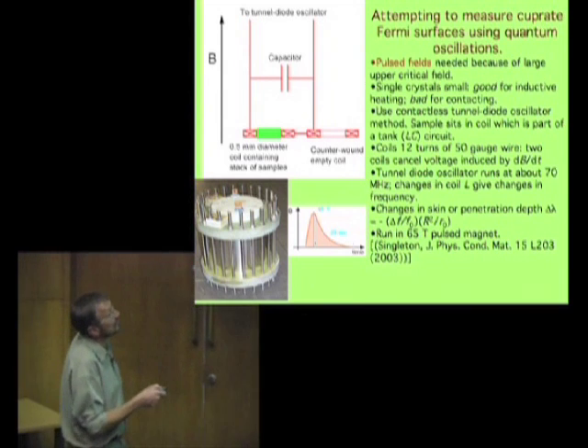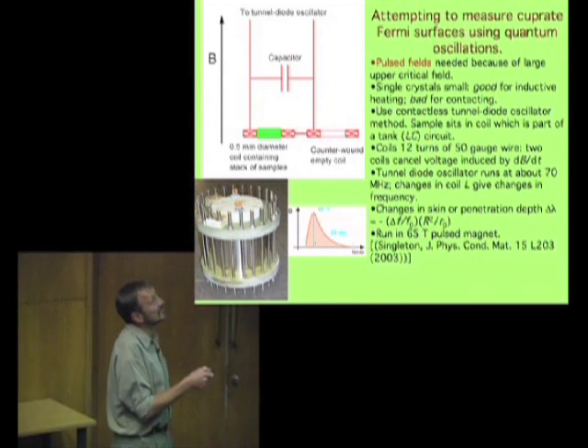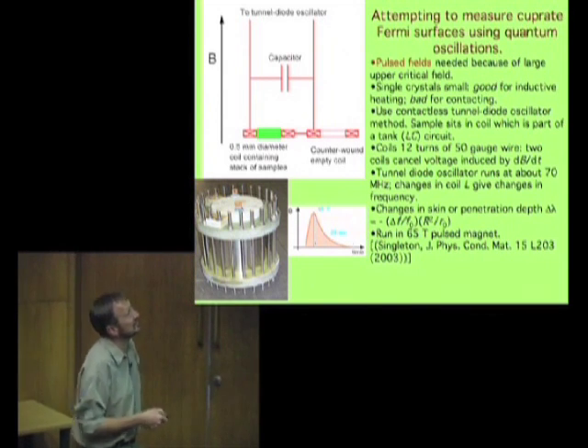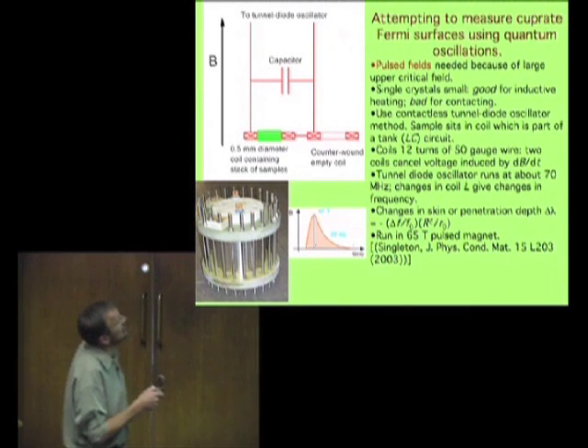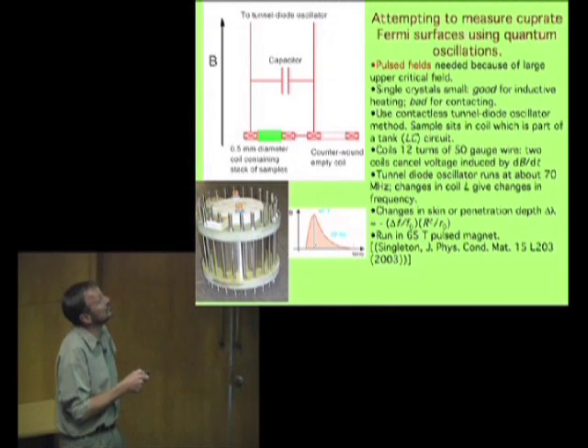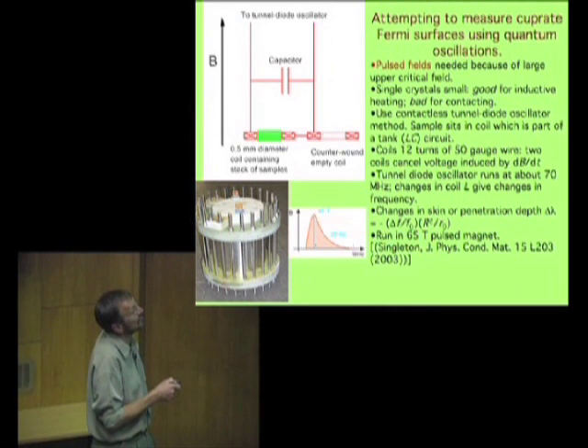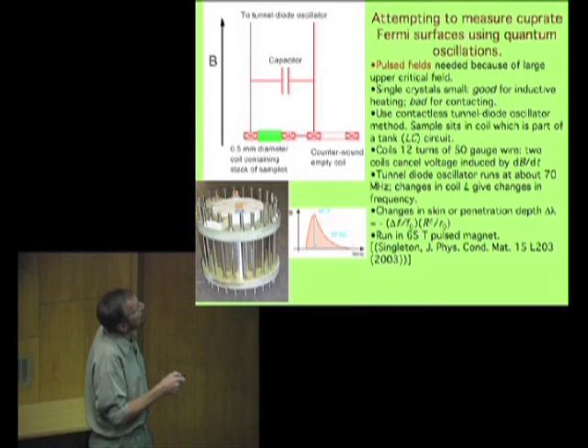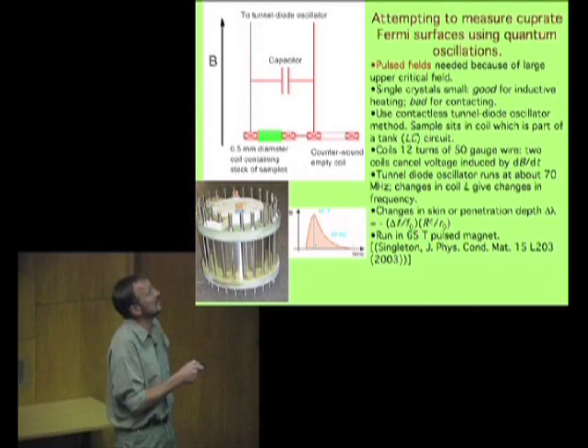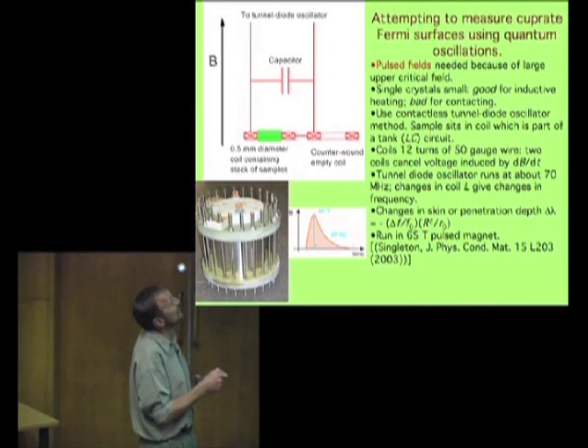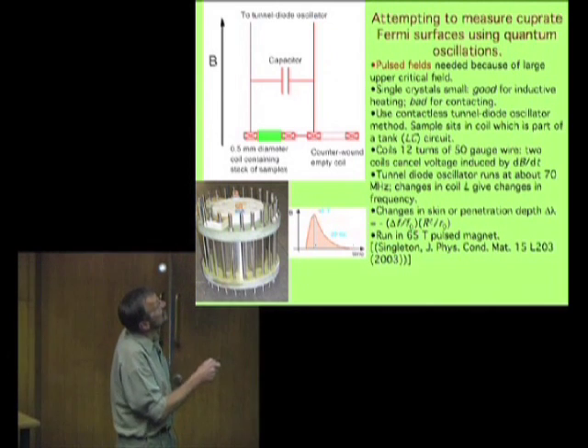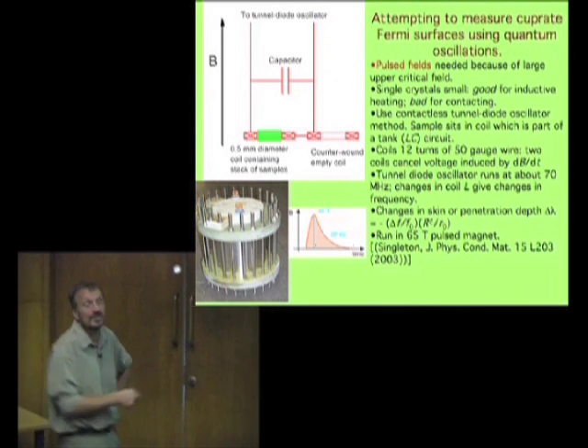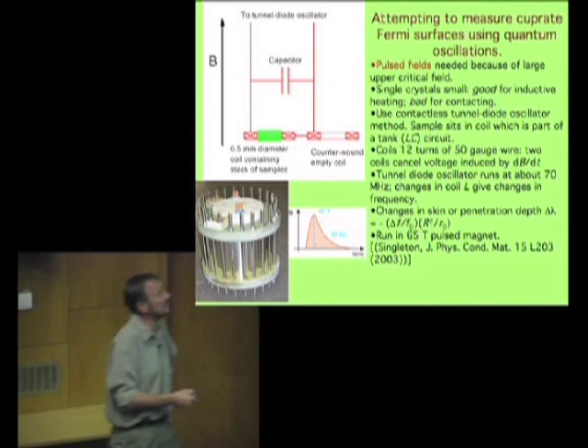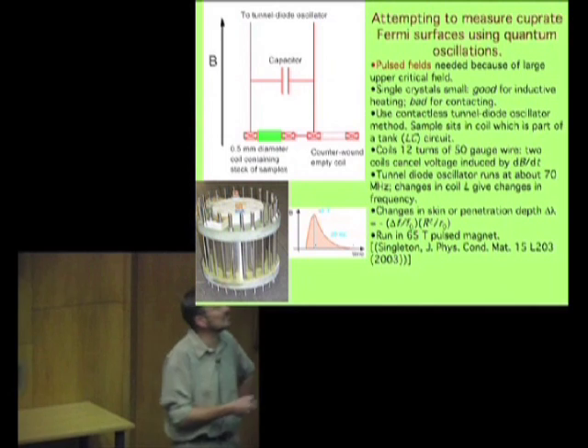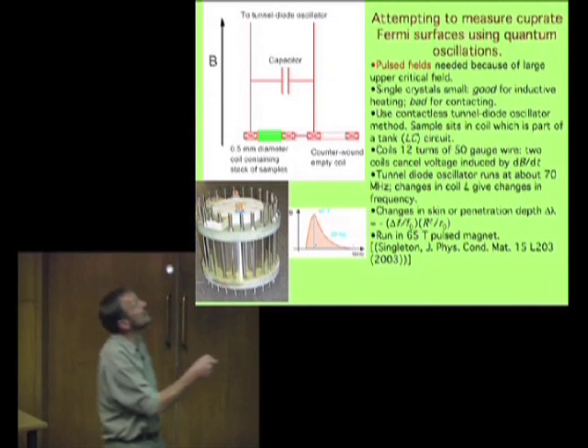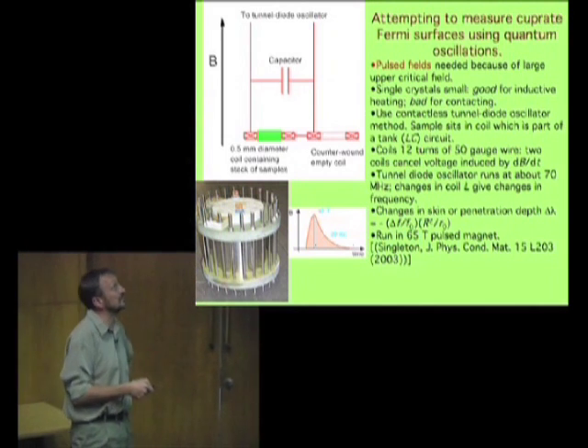So it's good that the crystals are small, but it's bad from the point of view of putting contacts on them. So what I do is I use a contactless method for measuring the conductivity or penetration depth. Here is the sample. It sits inside a 0.5 millimeter diameter coil, and the coil is part of a tank circuit. It's got a capacitor in there. A tank circuit has a resonant frequency, and so any change in something like the inductance of this coil will result in a shift in frequency.